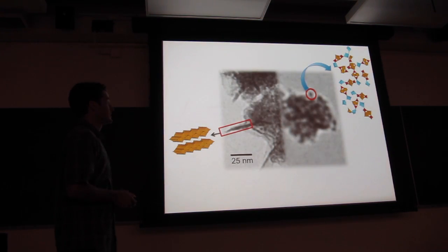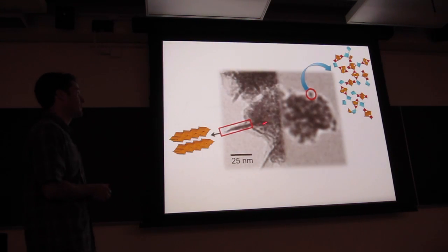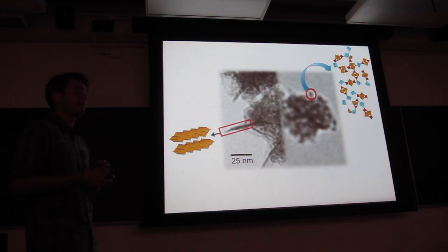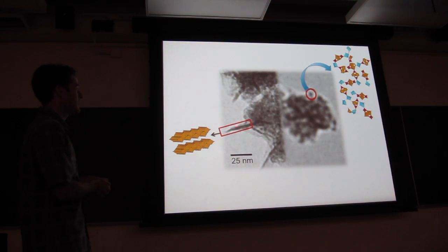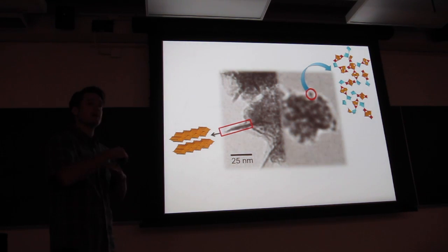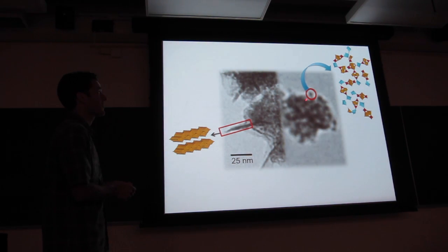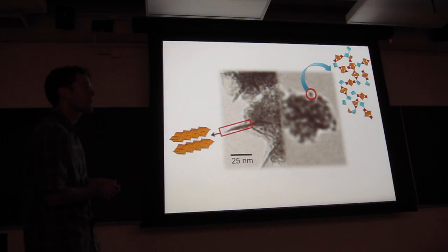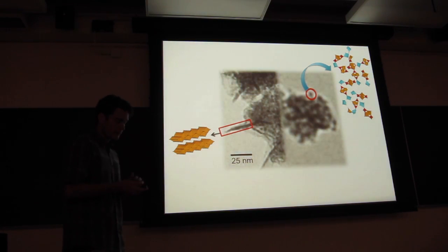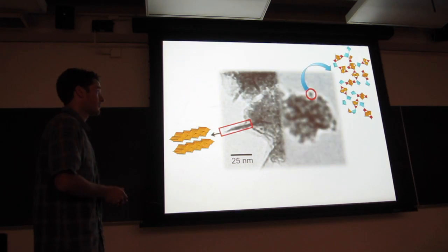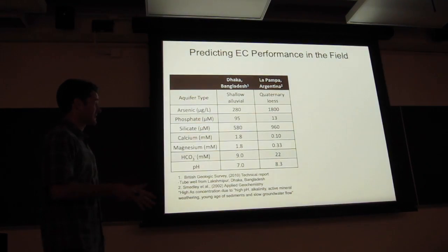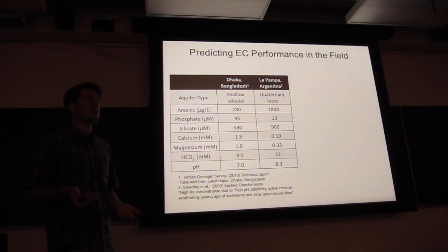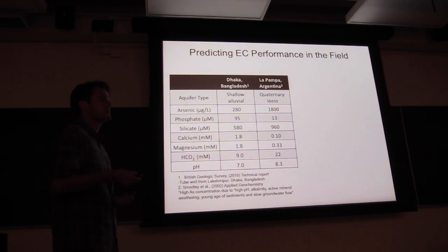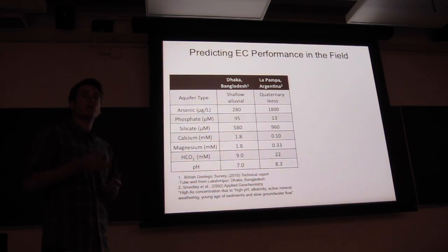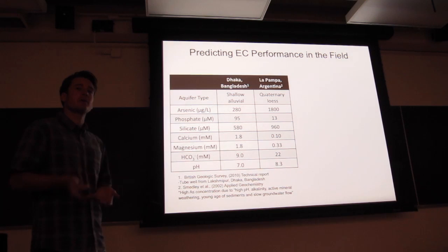All right. So now we can go back to our TEM images and we can really pin down the atomic scale configuration of both of these phases. So here this needle-like platelet is lepidocrocite with just a few coherently stacked sheets, and then this really small particle is an aggregate of these polymeric iron oxyhydroxides that have a really large oxyanion to solids ratio. Alright, so now one of the last things we can do, the implications of this work, is we can make much better predictions of how this technique will work in electrolytes with different chemical compositions.